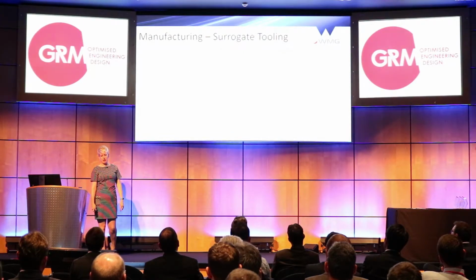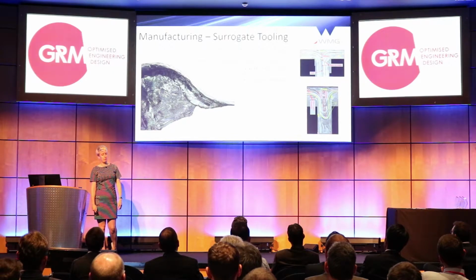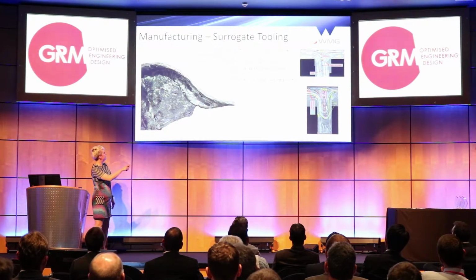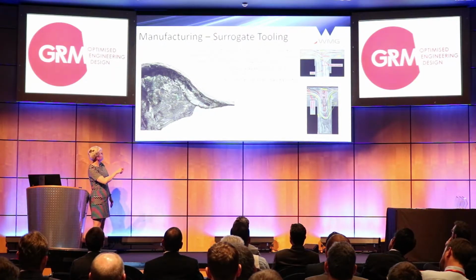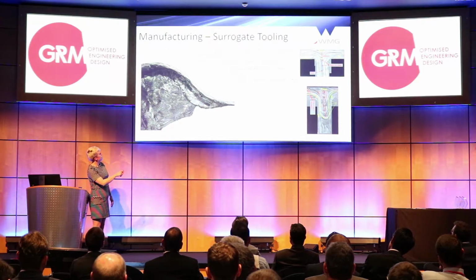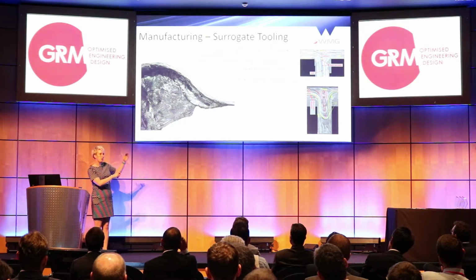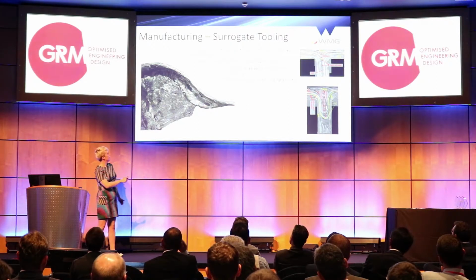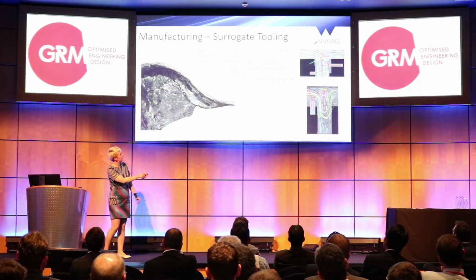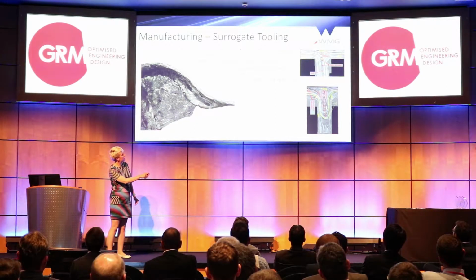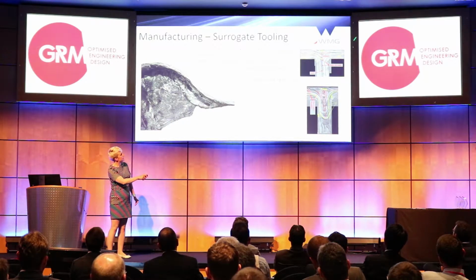So we got the parts back and we got them under the microscope. And I'll have to use my laser here. So this is pre-preg and this is SMC. And you can see here that the pre-preg has kind of impinged or been drawn into the ribs. We weren't expecting this. This is it under the microscope. So the yellow line kind of follows the interface between the SMC and the pre-preg.